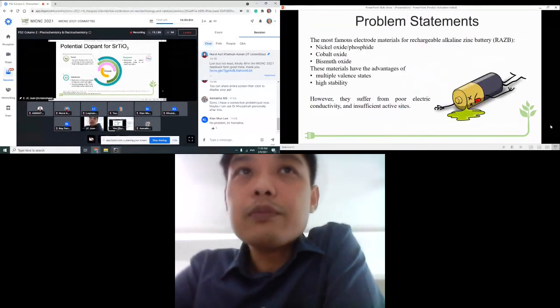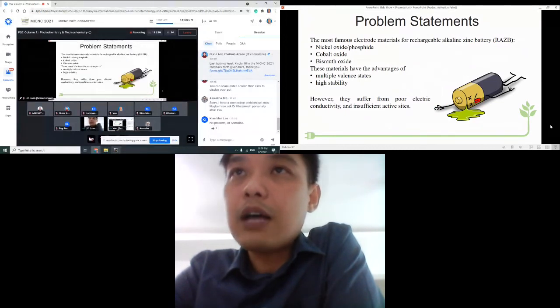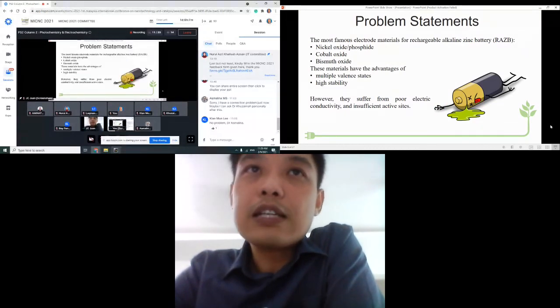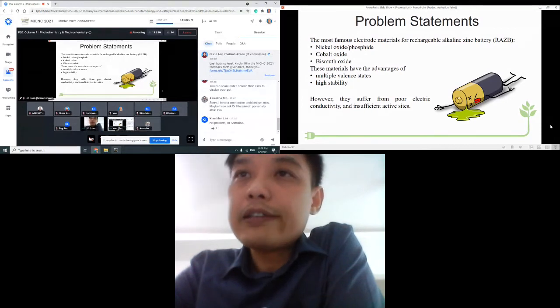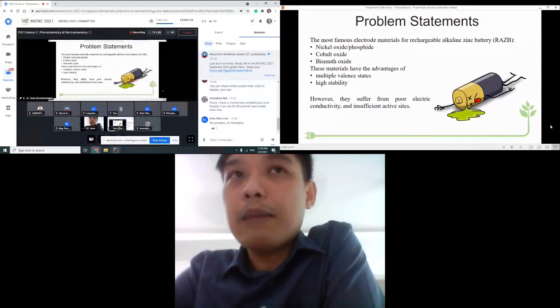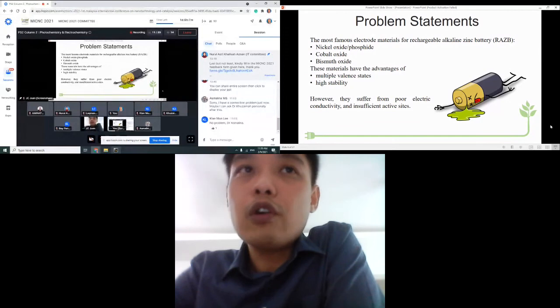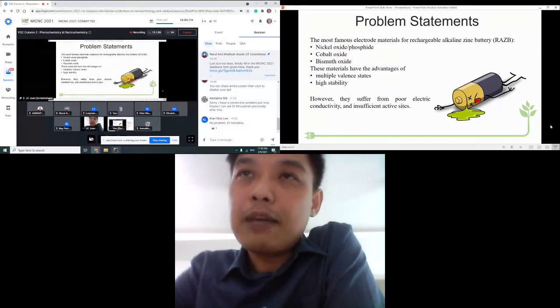So this is the problems. Most of these materials in rechargeable alkaline zinc batteries are using nickel oxide, cobalt oxide, bismuth oxide. They have saturated. There is no more improvement. People have tried a lot of other methods and materials and doping and so forth to improve the charge capacity of these materials, but it's still lagging behind.